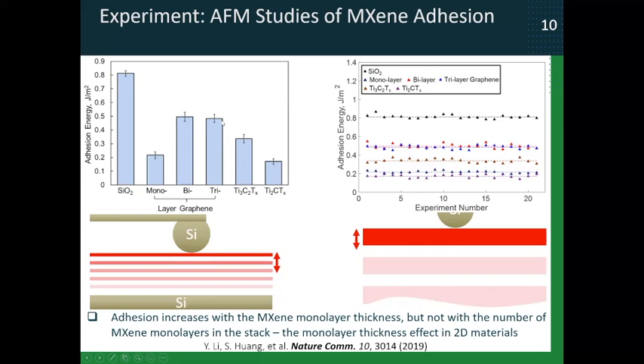For MXenes, what we found is that no matter how many monolayers you stack, so the data are shown here. So this is titanium 3C2, titanium 2C MXenes here. So no matter how many monolayers you stack, the adhesion force or energy in this graph is essentially constant.